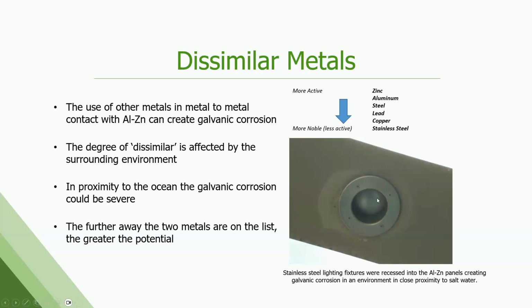This is a stainless steel lighting fixture recessed into a galvalume panel with no barrier between the two. So in direct contact, about 200 feet off the surf break outside of San Diego. And this corrosion developed within a year or two of installation. It's quite fast. If you peel that paint back, you will see that there's actually corrosion down to base steel occurring underneath. The paint is coming off because there's nothing left for it to adhere to anymore.